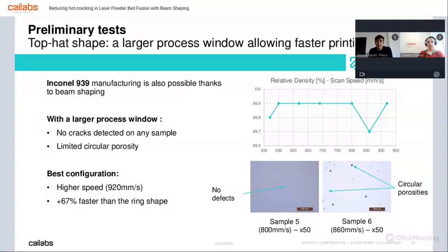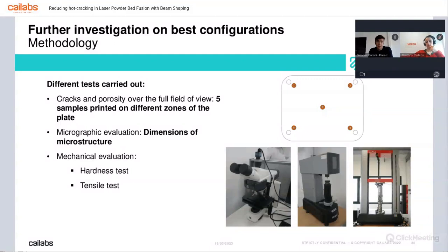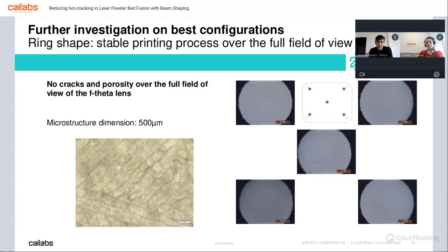So starting from this preliminary job for both the shapers, we wanted to observe if the laser beam shaper will introduce also uniformity on all the base plate. So what we have performed was to print several specimens around the base plate with the best parameters that we have found in the first approach, and see how the mechanical properties change and how the repeatability of no cracks and high density is obtained. In particular for the ring shaper, we have used the 550 millimeter per second scan speed, and we have seen that we can reach a high uniformity.